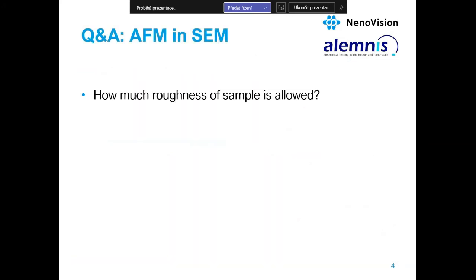The first question was how much roughness of sample is allowed? So the scanner range of LiteScope in the Nanoindenter configuration is 100 micrometers perpendicular to the surface. So the typical roughness values on the nanoindentation samples are usually many times lower.